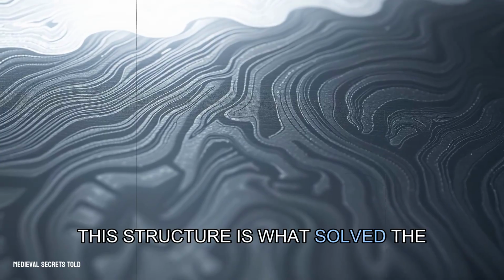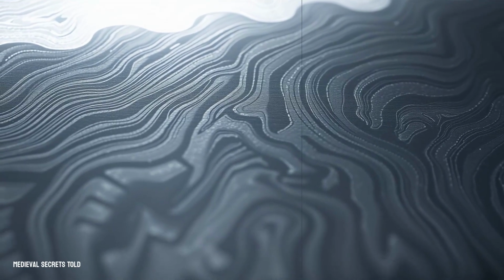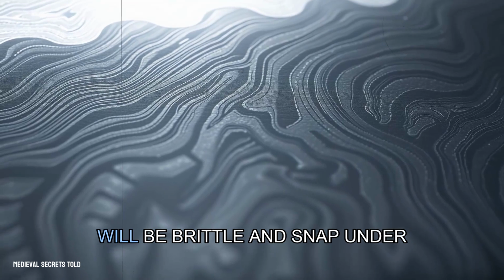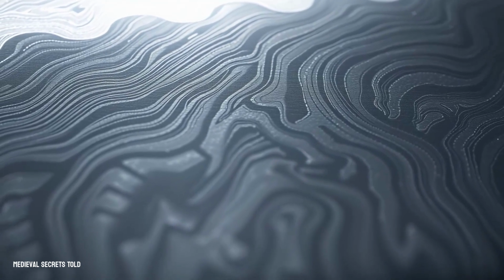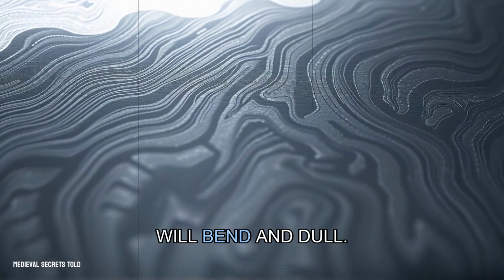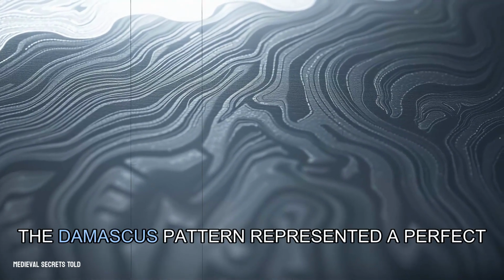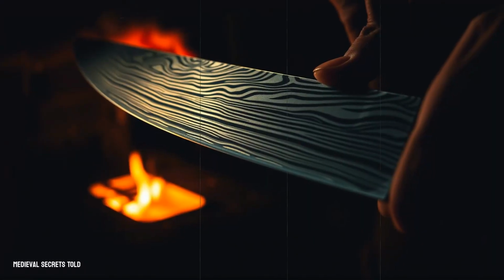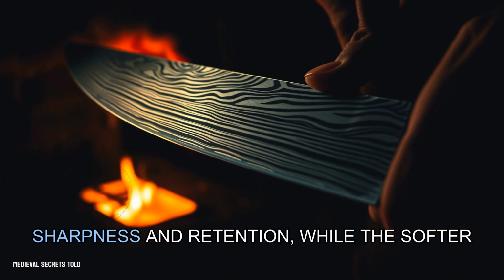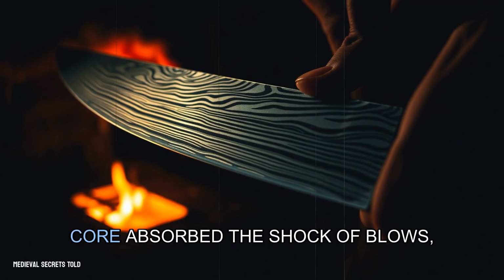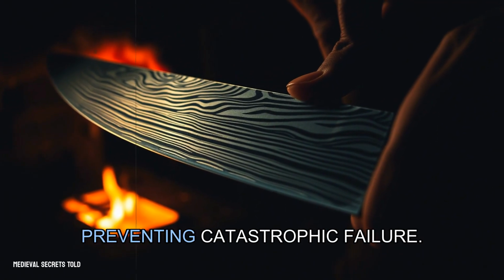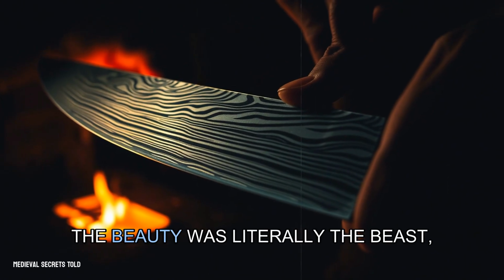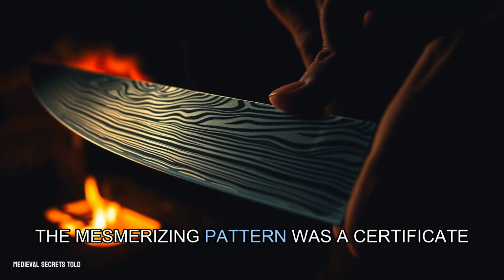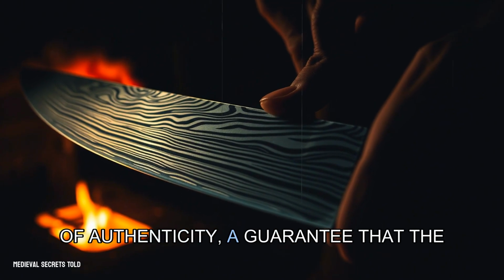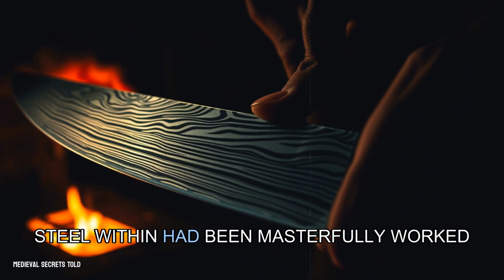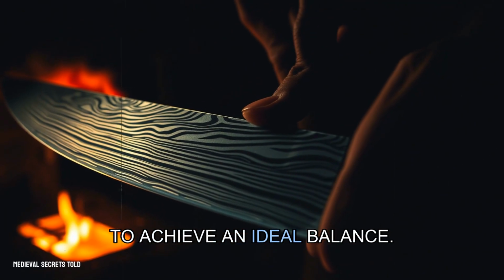This structure is what solved the ancient metallurgical dilemma. A sword that is uniformly hard will be brittle and snap under impact. A sword that is uniformly soft will bend and dull. The Damascus pattern represented a perfect gradient. It gave the edge its legendary sharpness and retention, while the softer core absorbed the shock of blows, preventing catastrophic failure. The beauty was literally the beast. The mesmerizing pattern was a certificate of authenticity, a guarantee that the steel within had been masterfully worked to achieve an ideal balance.